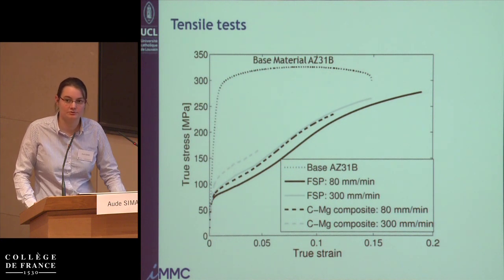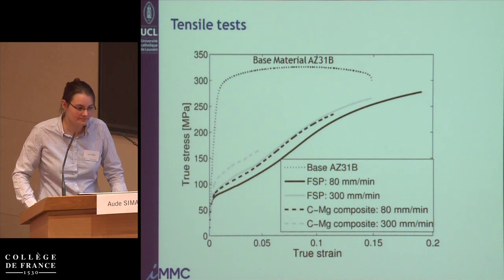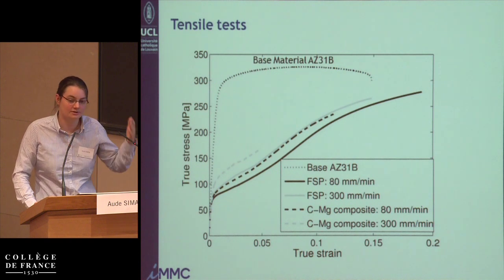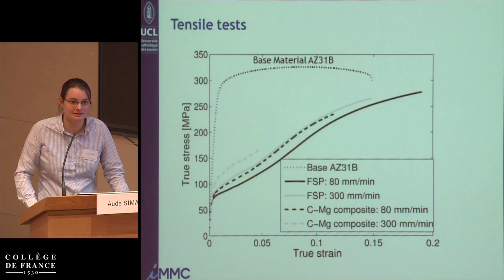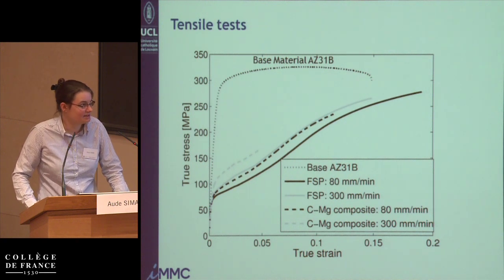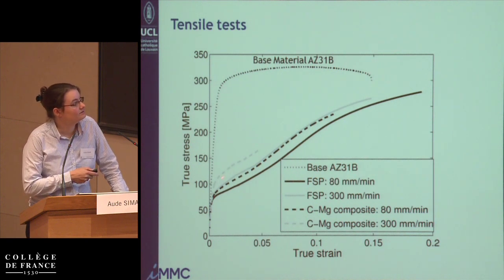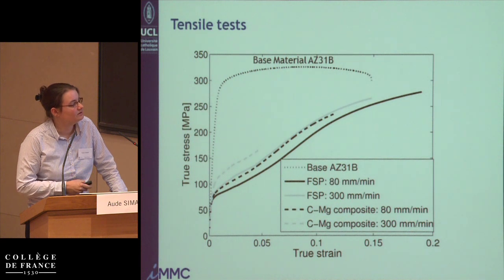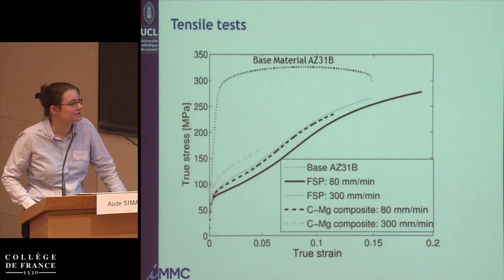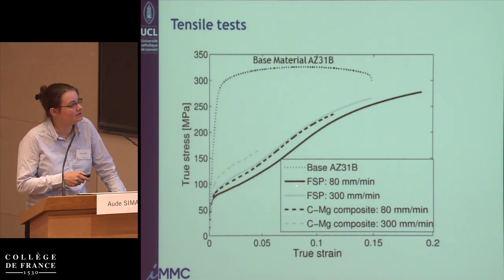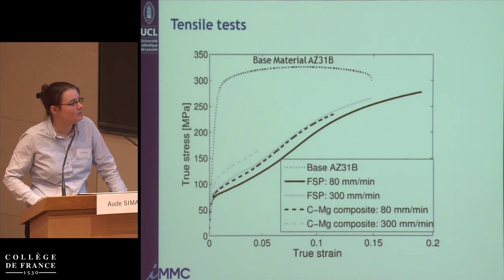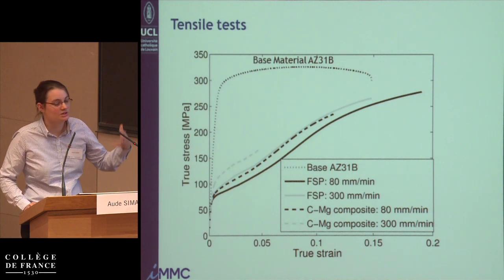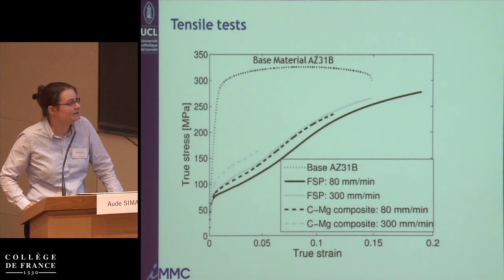But we could after the processing also roll these sheets and retrieve the capacities, the strength that the material had just due to its strain hardening. And also what you can see here is that the friction stir processing parameters have an impact on the strength that you reach. When you are at 80 millimeters a minute here, so without any carbon fibers, well, you are below a situation where you would be at 300 millimeters a minute. But in each case, you improve the mechanical properties, the strength of the material, by putting some carbon fibers in it.